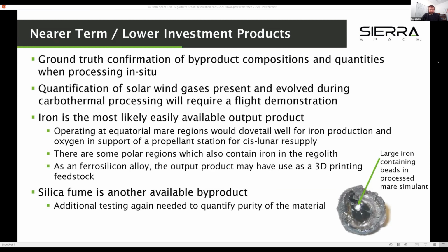Iron, I would say, is the most likely easily available output product. So we already know we're creating a good amount of that with the mare. If you had a cislunar refueling depot or something, that would give you a good reason to have oxygen production at the equatorial region, and then you could produce a lot of iron from that. There are some polar regions, per my understanding, that also have some iron. And then I've also seen some research that indicates if you have the ferrosilicon alloys, those can be used as a feedstock for 3D printing uses. And I talked about the silica fume, but I do think that's a very interesting avenue for already having a partially purified, easy to get to product for silica. Next slide, please.